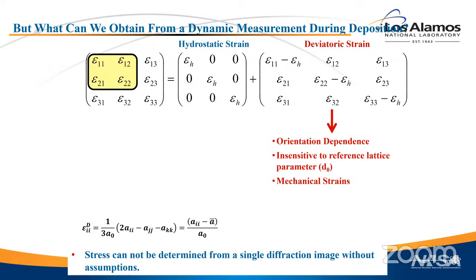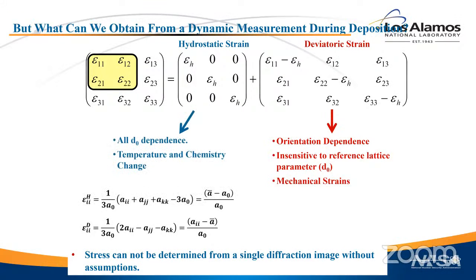By subtracting out the average the way I've done here, the deviatoric strain is only linearly related to the reference lattice parameter A0. Well, that only changes a little bit, so a proportionality there isn't a big deal in the uncertainty. The problem comes in the hydrostatic portion, which is here. Now you're doing a subtraction between the average lattice parameter and the reference. That difference in itself is very small. So if you're uncertain on A0, the reference lattice parameter, when you take a subtraction, that uncertainty becomes very important, right? When you're just doing division by A0, it's not so important because it's just linearly related. But when you're subtracting two things that are very close, that becomes a driving problem in your uncertainty.